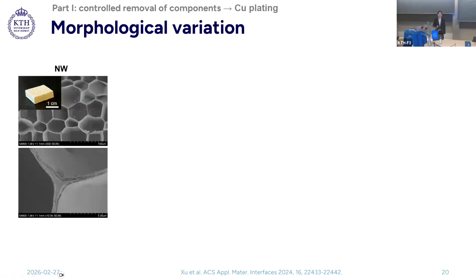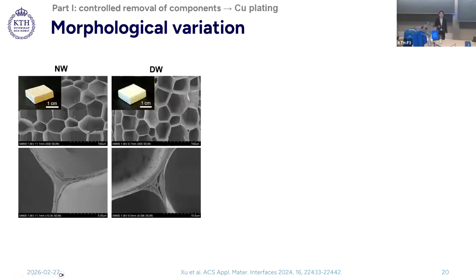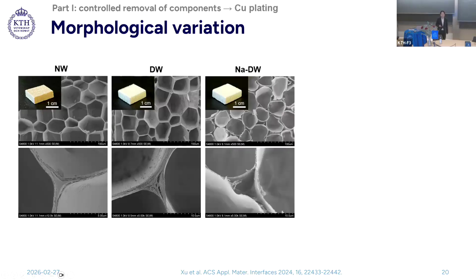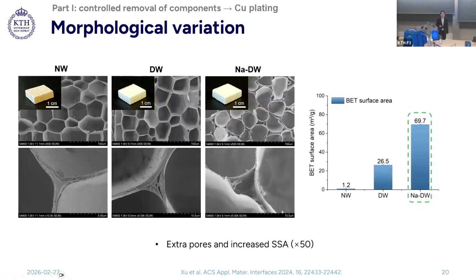Using scanning electron microscope, we can observe the microstructure change on the cell wall. Delignification generates pores within the formerly lignin-rich middle-lamellar region. The subsequent sodium hydroxide treatment disrupts the intercellular connections and creates extra pores. The corresponding specific surface area greatly increased from 1 square meters per gram of native wood to 70 square meters per gram, showing the efficiency of cell component removal.